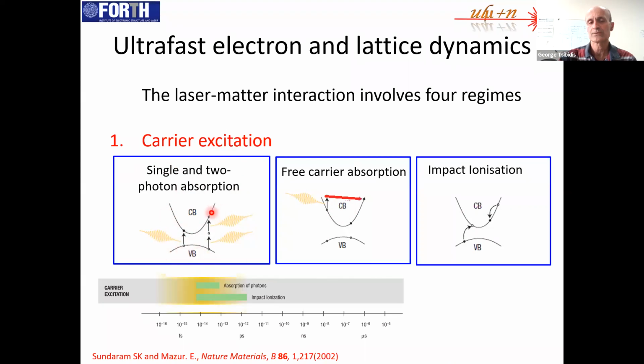Here's the valence band, and here's the conduction band. Here's the pulse, and these arrows show the transition of the electrons from the valence band to the conduction band. So you see that if the photon energy is sufficient to excite an electron through a single photon absorption, then we can have this excitation, but then we can have a secondary process where the electron requires a two photon absorption in order to reach this level. So you understand that this occurs with a smaller probability than this one. But of course, if the single photon process cannot occur because the photon energy is small, then the second one should occur. Then we can have a free carrier absorption.